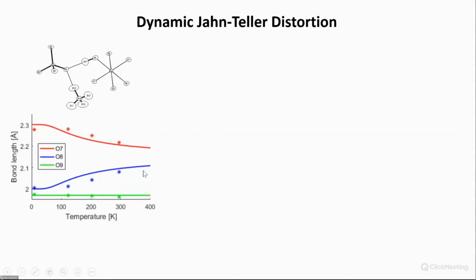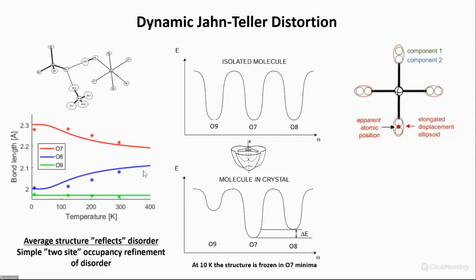And you'd say, what is going on here? It turns out the copper Tutton salt is a famous example of what's called a Mexican hat potential. If you have the isolated copper ion with the six waters, you will have a potential surface where you can elongate along each of the Jahn-Teller axes, and they would have the same energy. But when you're inside the crystal, there is no isotropy, so the elongation in different directions will have different energies. And it turns out here that the O7 has the lowest energy.